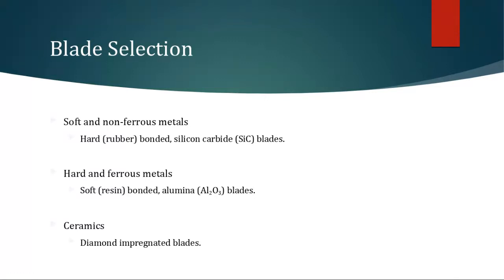So for soft and non-ferrous materials, so your aluminums, titaniums, copper, you're going to use the hard silicon carbide blade. There's your hard bonded, okay? And hard meant it would last longer. It doesn't deteriorate quickly, okay? So you see in the hard and ferrous metals, so hardened or stainless steel, quench and tempered, some of your tool steels, those materials you're going to be cutting with a soft bonded blade, so the one that wears away quickly. And then for ceramics, you have your diamond impregnated blades, and those are typically cut on the precision wheel for any type of ceramics.